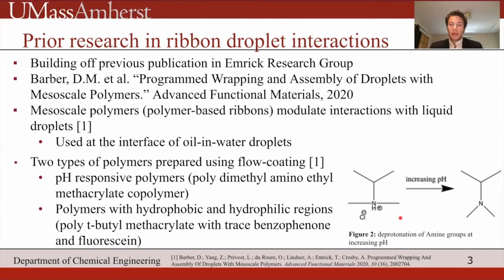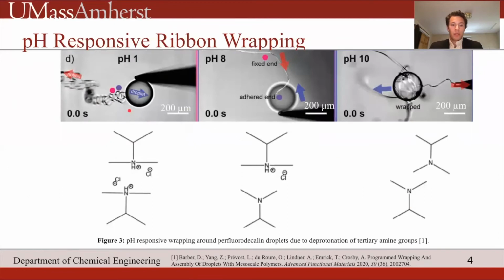Shown here in figure 2 is the pH-responsive component of the first polymer that I mentioned, in which at an increasing pH, the amine groups deprotonate, and they therefore become more hydrophobic and are more easily able to interact with hydrophobic fluids, such as perfluorodecalin oil. And so shown here at a low pH, when these amine groups are not deprotonated, the polymer ribbon extends in solution, but does not physically wrap the droplet. At a pH of 8, when some of the amine groups in the polymer backbone are deprotonated, we start to see some wrapping of the oil droplet, but we still see a good deal of extension in the solution. And at a pH of 10, we see the entirety of the oil droplet wrapped in deprotonated amine groups.